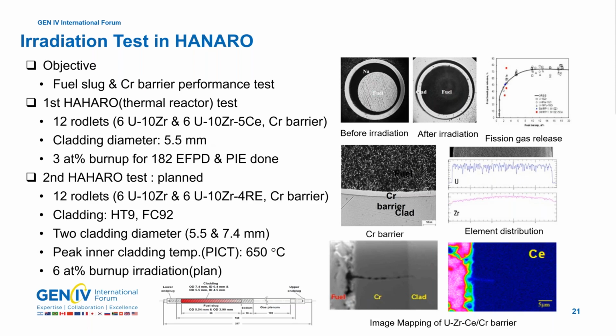First one, we were very careful. This one was irradiated at low burnup, also at low temperature. The maximum cladding temperature was about 550, so it's good. There was no pin failure in this first one. The second one we fabricated was designed to reach a higher inner cladding temperature and to achieve higher burnup. But even though we completed the fabrication, we are still waiting to be irradiated because of some operation problem in the Hanaro reactor.